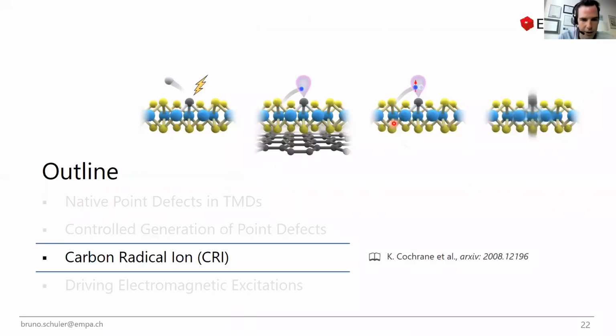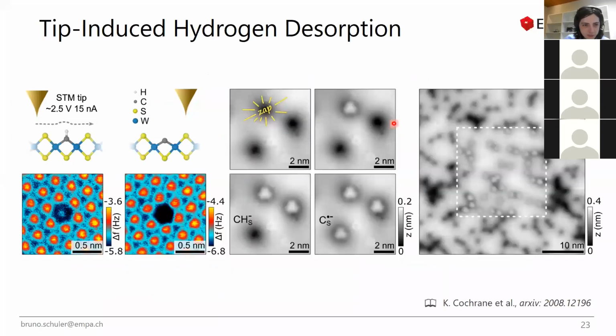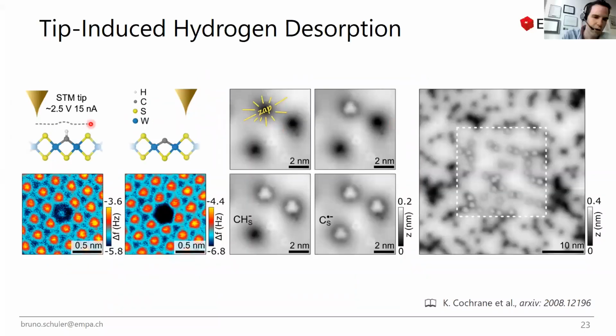There is some other aspect which is quite interesting to it, and this is we can remove the hydrogen atom from this carbon hydrogen complex. So we start out with this carbon hydrogen that we can implant selectively through chemical means. And then we use our scanning probe tip and apply a high bias and a high current to it, so we can peel off this hydrogen atom. This is quite a selective and very reproducible process, so you can go one by one and you see only this type of defect changes from this dark looking thing to something which looks like an orbital. You can also do this on a bigger scale by just going around with your tip at high bias and do this all over the place.